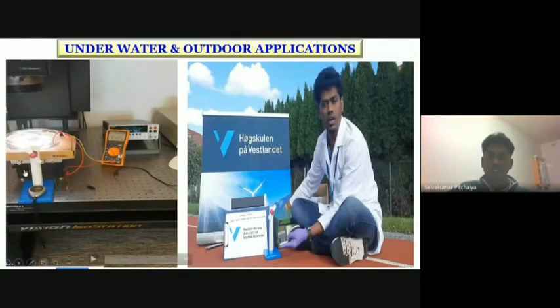When you are working, we also tried without encapsulation as well. That couldn't withstand even for 5 days. So it degraded, because lead is highly reactive to water moisture. It easily dissolves in water. That's the major criterion. And you also have the organic component in the structure, which is easily hygroscopic and very highly sensitive towards temperature. So both are major enemies. Water and temperature are the major enemies for this perovskite structure, and it is very difficult. For that we are struggling, in terms of commercialization.